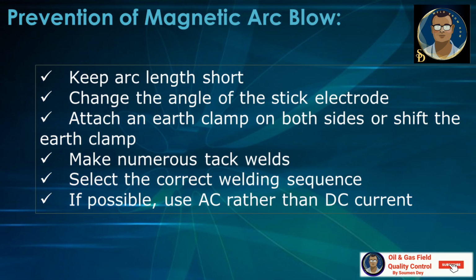How to prevent this? Keep the arc length short, change the angle of the stick electrode, attach an earth clamp on both sides or shift the earth clamp. Make numerous tack welds. Select the correct welding sequence. If possible, use AC rather than DC current. AC has frequently changing polarity, so magnetic arc blow is absent in AC welding.